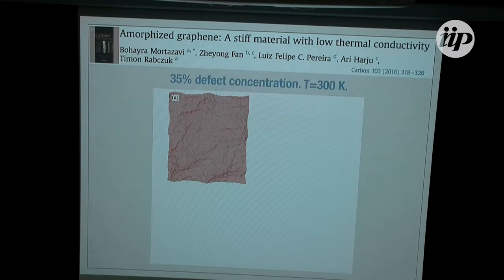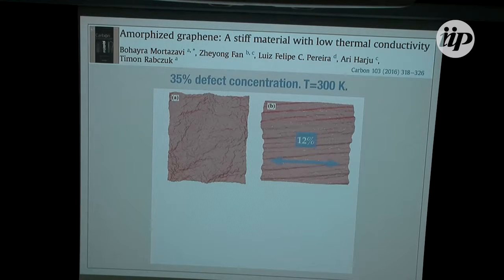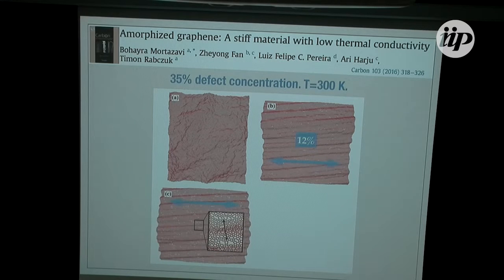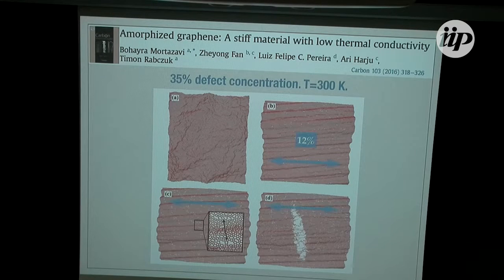So first thing we did was to stretch it. We start stretching it in this direction, and up to 12%, that's when we start to see some breakage. If we look very close, you start to see the formation of these large voids. And then if we keep stretching from there, eventually it breaks.